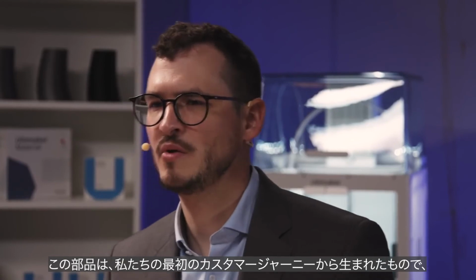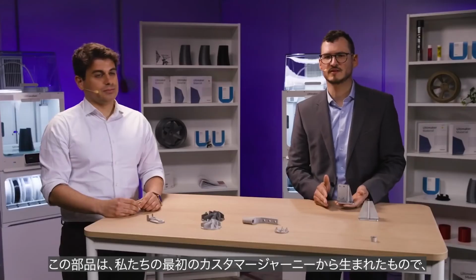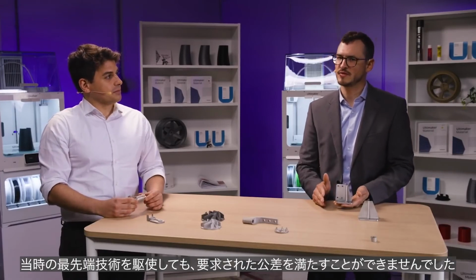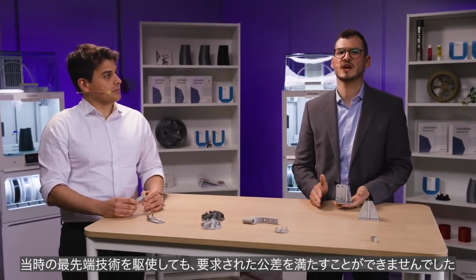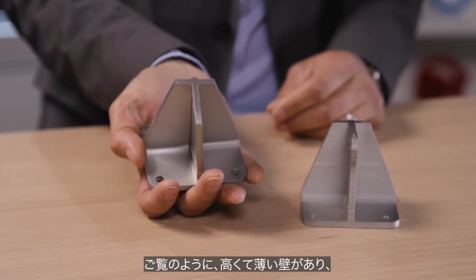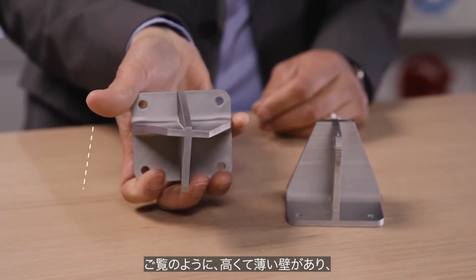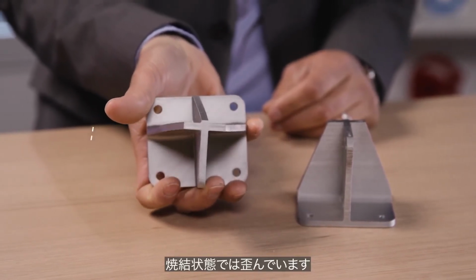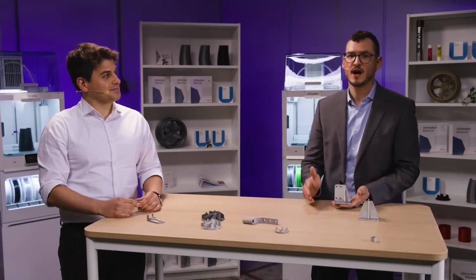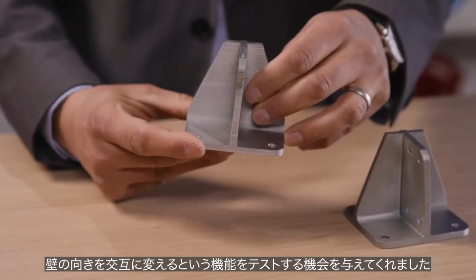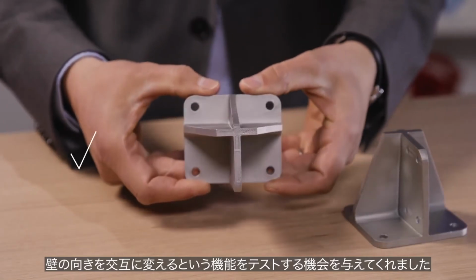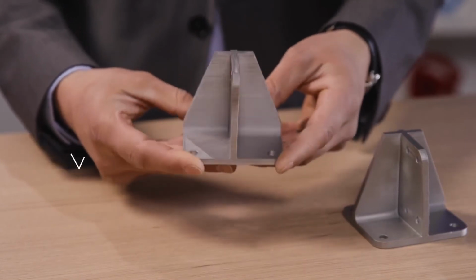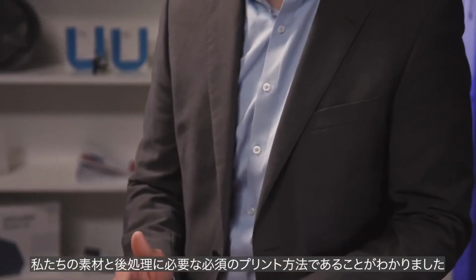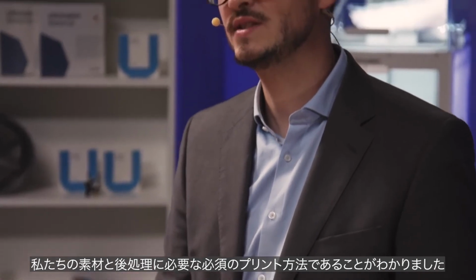This part comes from our very first customer journey, where we did not succeed to meet the desired tolerances, even though we did everything right from the state of the art at that time. As you can see, we have high and thin walls, and in the sintered state, it's distorted. As you might remember, you gave us the opportunity to test the feature of alternating wall directions, and it worked on the first print. Since then, we knew it is a mandatory way of printing, which is needed for our material and post-processing.